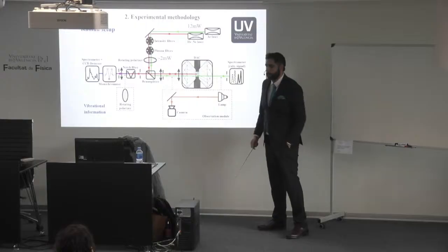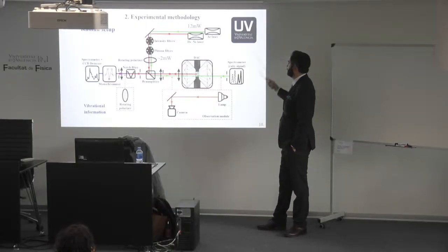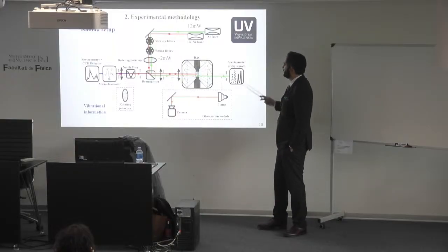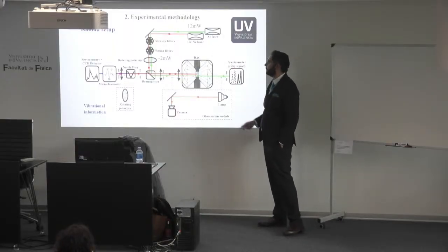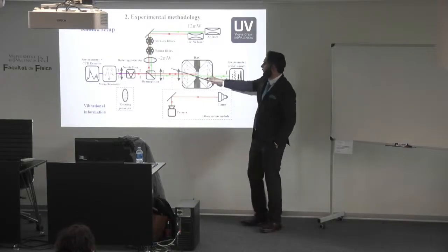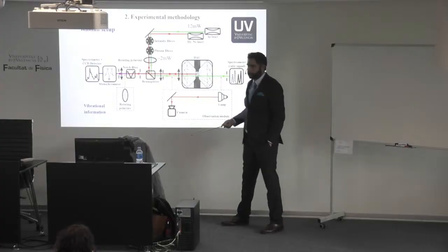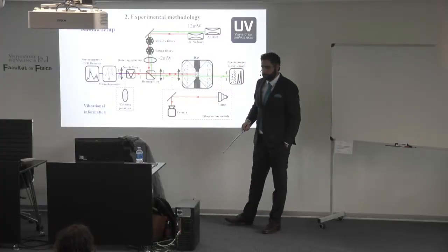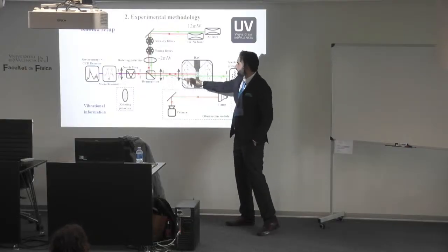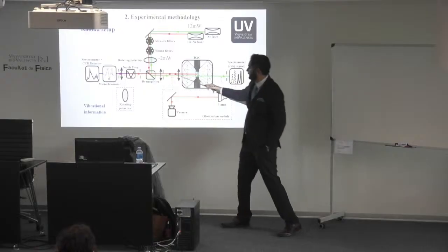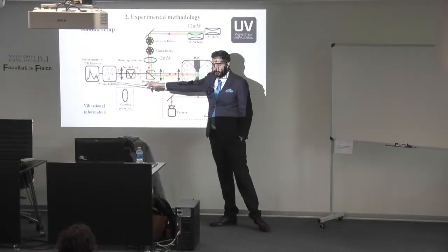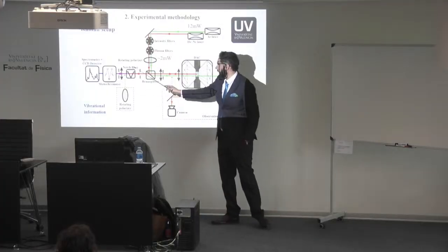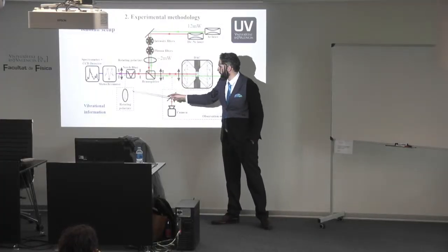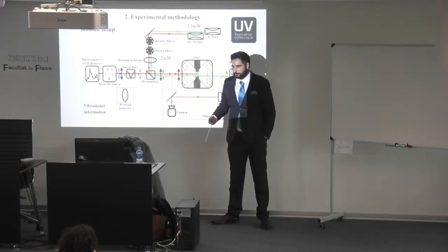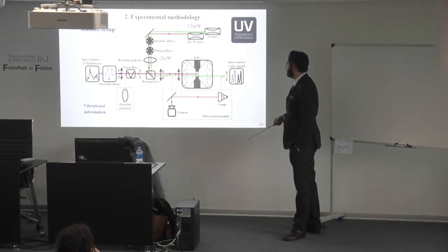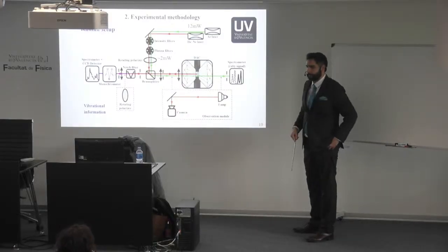Then we also have Raman results. Most of them were measured here in the university. In this case, we have two lasers with a power of 2 milliwatts, but this is too much, so with a rotating polarizer, we get it down in order not to burn the sample. We need some filters in order to have a good signal of just the laser. Then, in the beam splitter, it goes into the sample and reflects the signal, and it's filtered in order to get the Raman signal. But we can also add a rotating polarizer, and with this we can do polarized Raman measurements. But well, this is more or less the setup that we use.